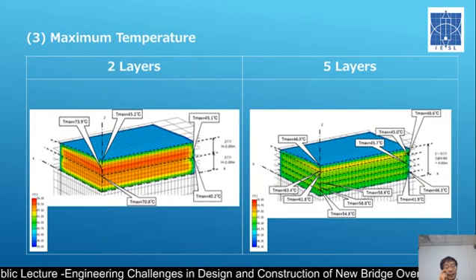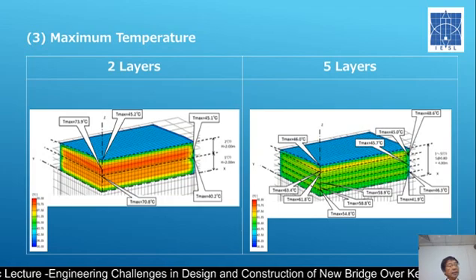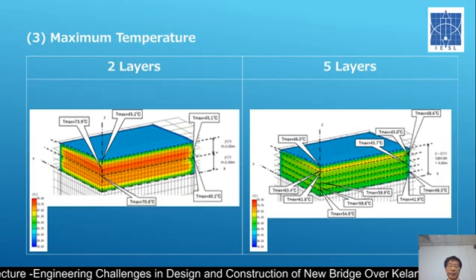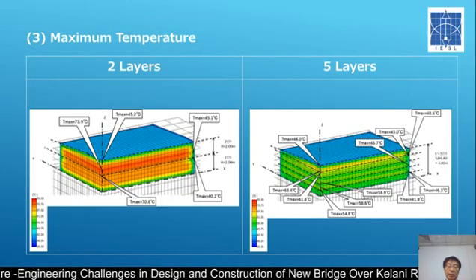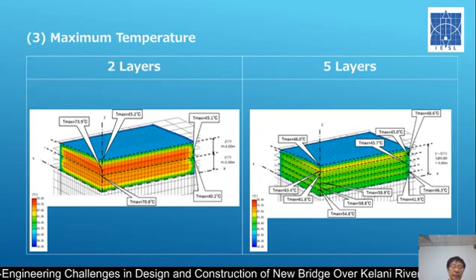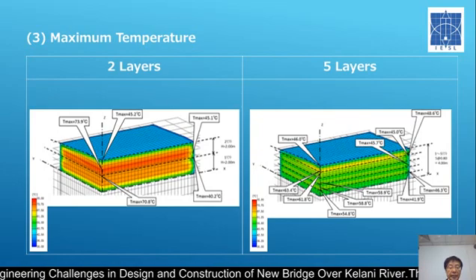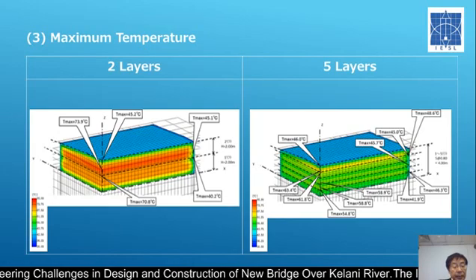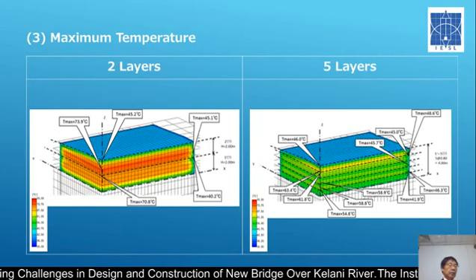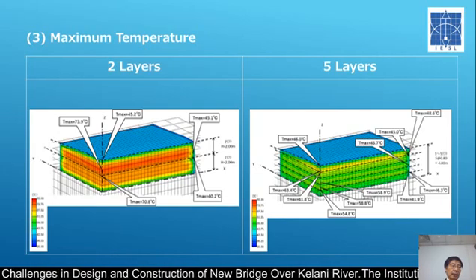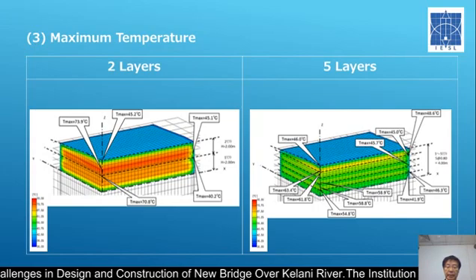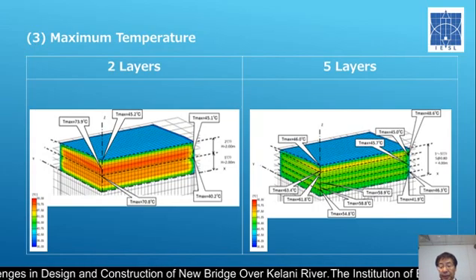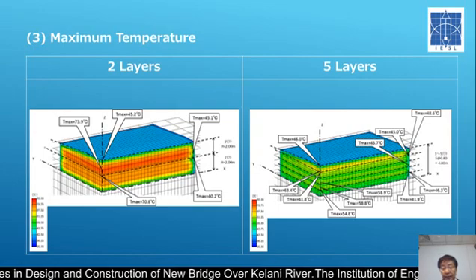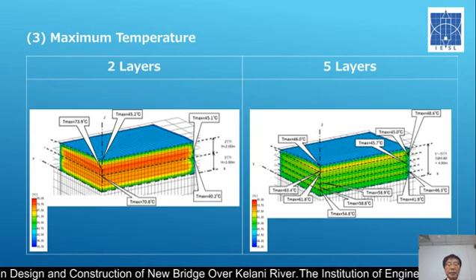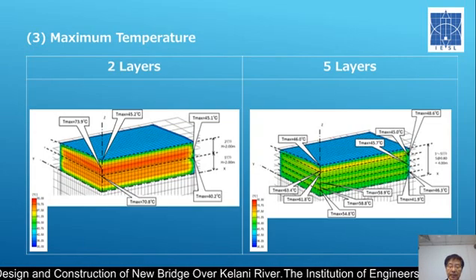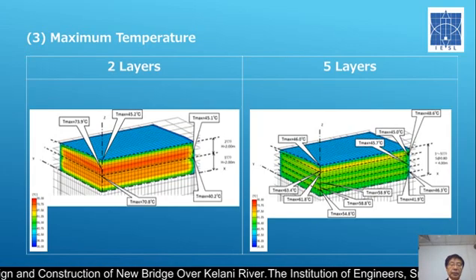This is an analysis result. The red is usually not good conditions, higher temperature. Green or blue is low temperature. And on the left hand side, in the analysis, the temperature is 74 degrees, which is almost close to the 75 degrees. Whereas with 5 layers, the temperature is only 63 degrees, much lower than that. That means more allowance for the temperatures.